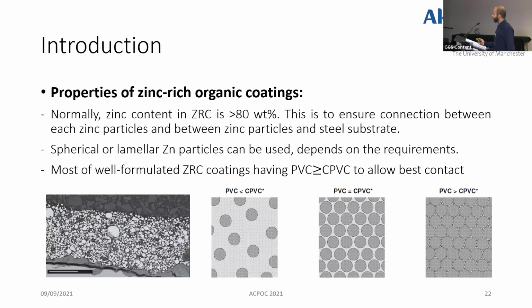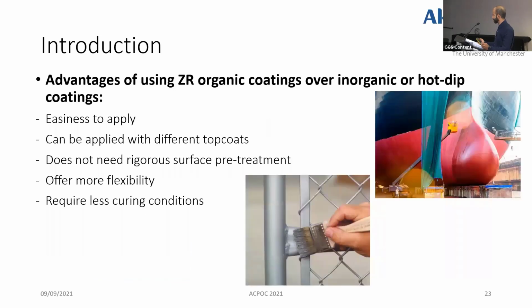Zinc-rich organic coatings offer some properties. For the galvanic action to work properly, the zinc loading must be very high, not less than 80 to 88% in the coatings. And this is to ensure the connection between each zinc particle and between zinc particles and the steel substrate. Both spherical and lamellar zinc particles can be used. Actually, if you use different sizes of spherical particles, this may give you better galvanic action, better connection. It depends on the requirement of each coating. But in most well-formulated zinc-rich organic coatings, the PVC is greater than or equal to the critical pigment volume concentration to allow the best contact between each zinc particle.